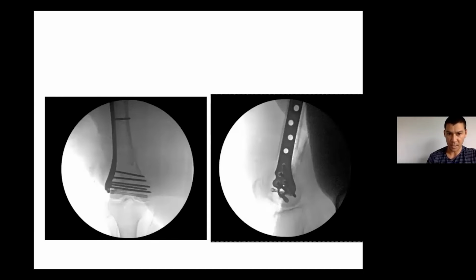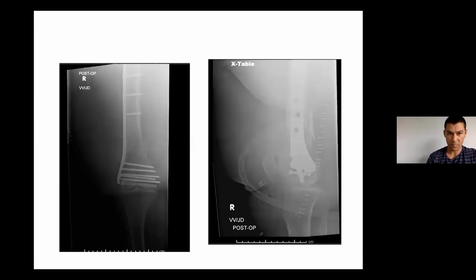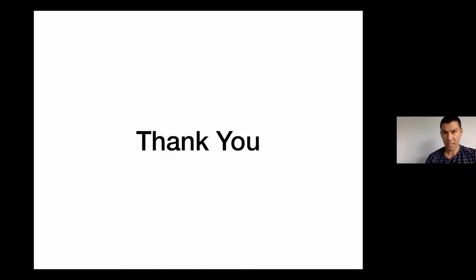And again, I did actually put a screw intentionally through her notch because that was the only place where there was some reasonable bone to hold the articular reduction. And so that's how she ended up. The one nice thing is the intramedullary device really holds the reduction during the percutaneous plating almost perfectly. So you're really just using the percutaneous plating portion as like a sawbones exercise. And that's it. Thank you very much.